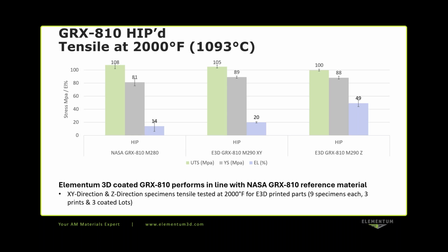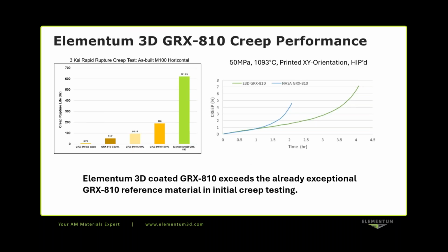Again, you can see the Elementum 3D coated material is performing, I would say, very in line or even potentially superior to the baseline data. So this is really exciting because this material is fantastic in creep performance, and that's one of the really outstanding characteristics of this material. And we found that in our creep testing, the Elementum 3D coated material is even exceeding NASA's already great